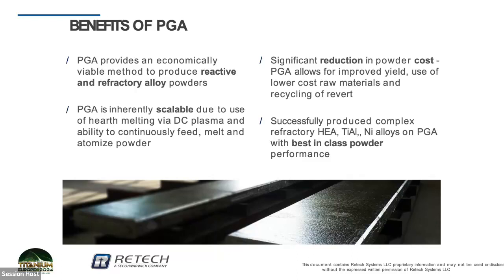Overall, we are able to control the costs by improving the feedstock requirements, the ability to control particle size distribution, which is critical. And then the ability to melt in a plasma system opens up the types of alloys you can produce. Because of the flexibility of feed, you don't have to pre-alloy your feedstock, which allows you to use complex feedstocks to alloy in situ in the hearth.